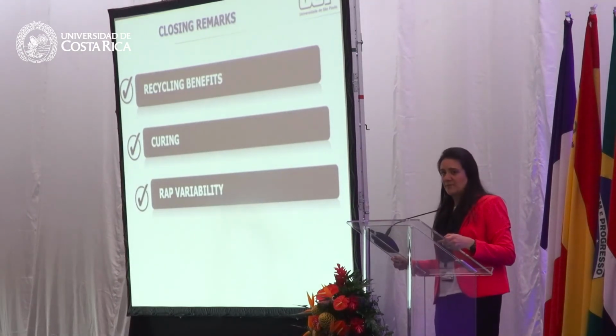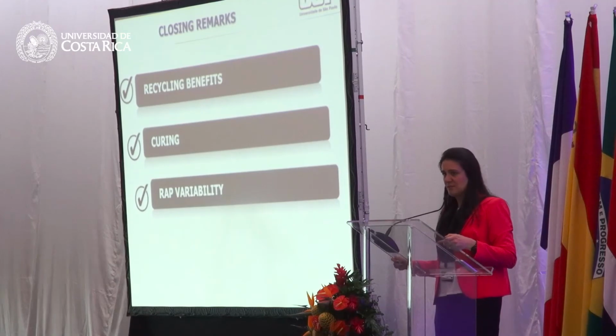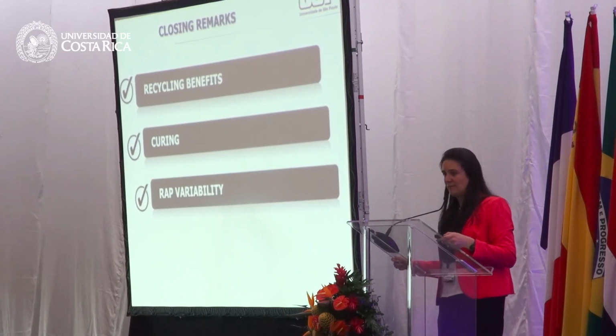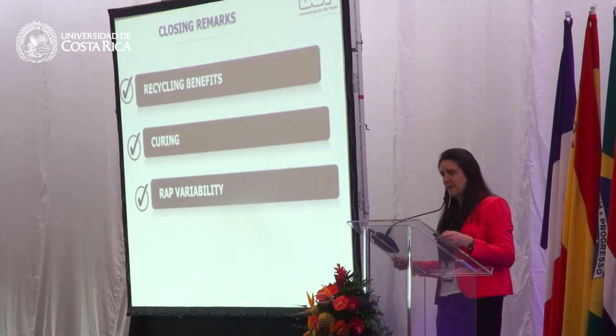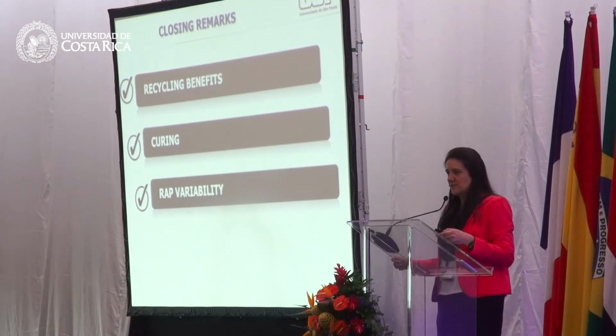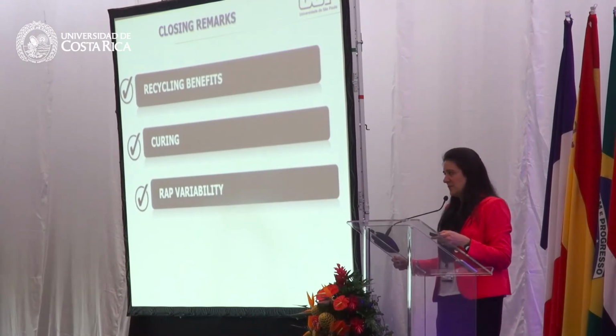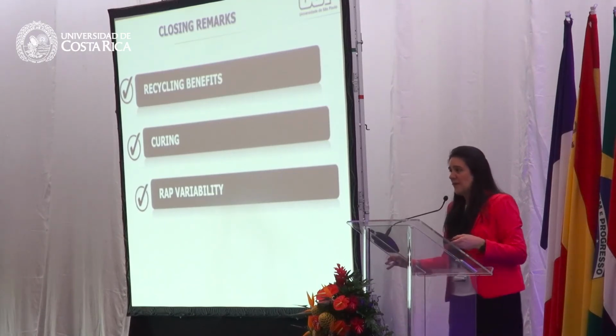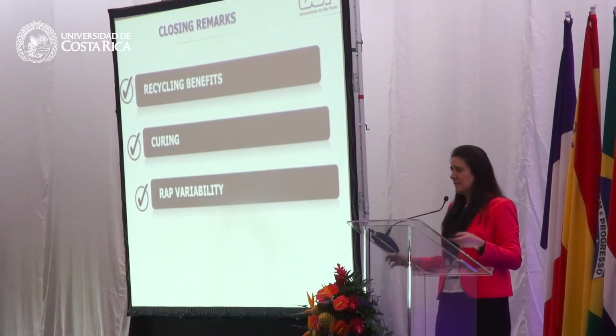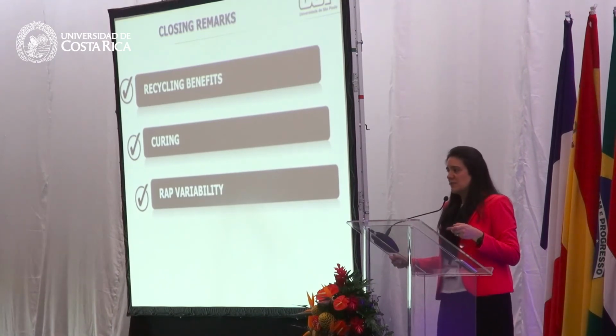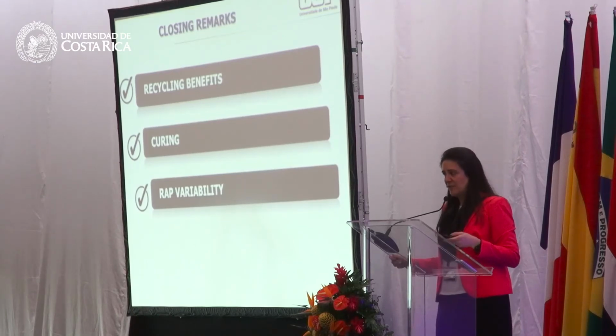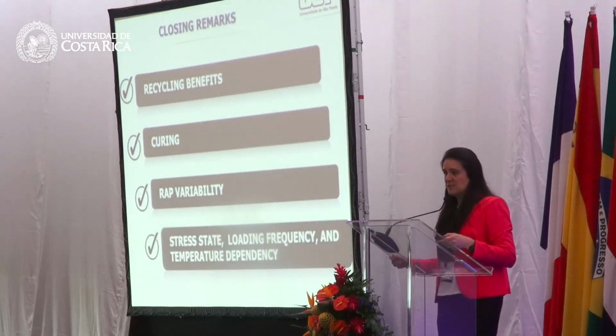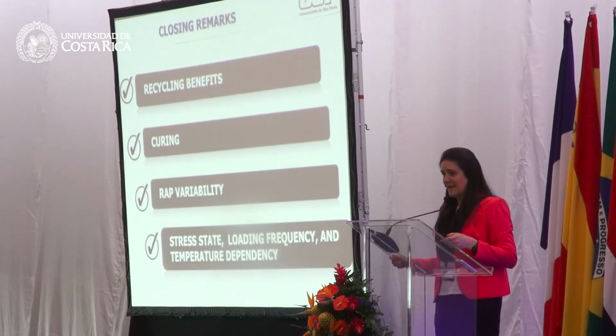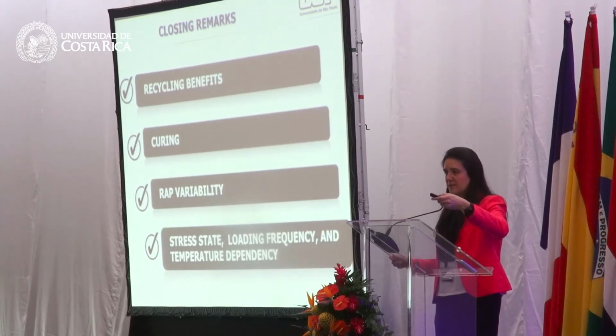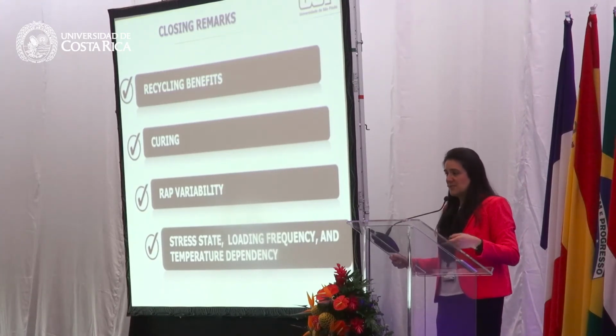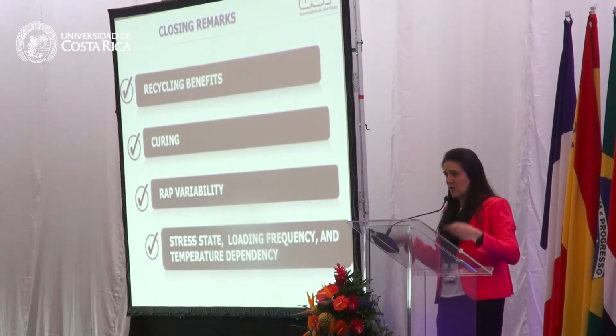You have to account for RAP variability. It happens a lot in Brazil. We can have RAP with neat binder, with modified binder, with 19 millimeters asphalt mixture, with 9.5 millimeters asphalt. So you have to deal with that. So if your RAP has a very high variability, maybe it's better to consider this design in a plant and not in the field. And this material, depending on the amount of binder, by binder I'm saying the hydraulic binder and the bitumen, can be stress dependent, time and temperature dependent, all this together.